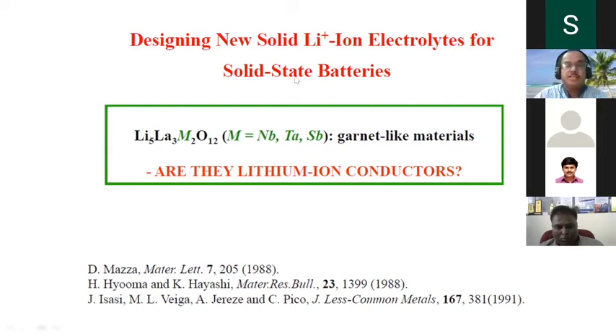They were very much interested in making the materials by powder oxide reaction. They published the results. So it's a new compound. Like that, they found these lithium garnets, Li5La3M2O12 with niobium, tantalum, and antimony. They synthesized them by very simple techniques, and just by powder oxide reaction, this could be a possible structure.